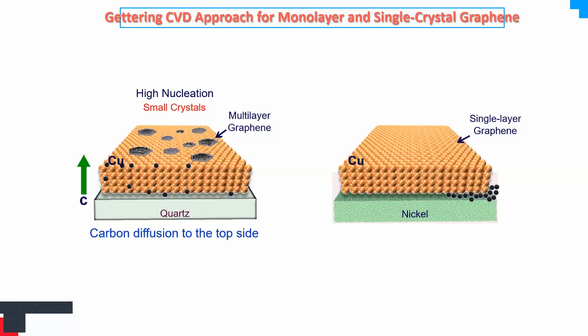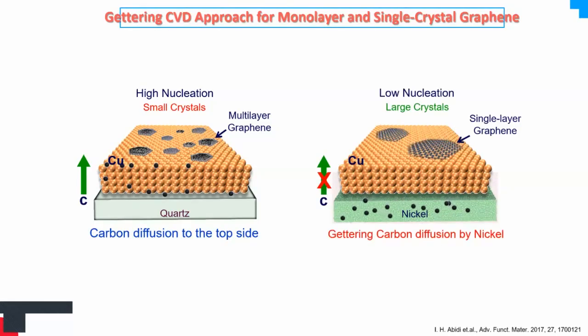So then the copper foil creates a lot of multi-layers, and also because once you have more carbon everywhere, it creates a lot of nucleation sites. So you have more nuclei of graphene, a high nucleation density of graphene crystals. But once we put it on the nickel-copper, all the carbon on the backside is getting into the nickel, so it's not going up. So we mostly have a single layer of graphene on the top. And second, we are also getting larger sizes because we're controlling nucleation density on the top as well.